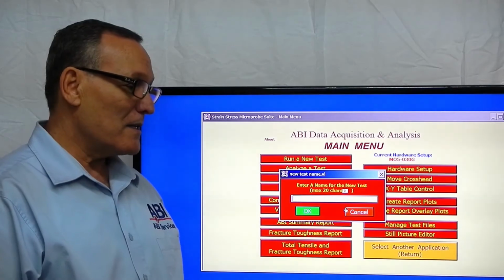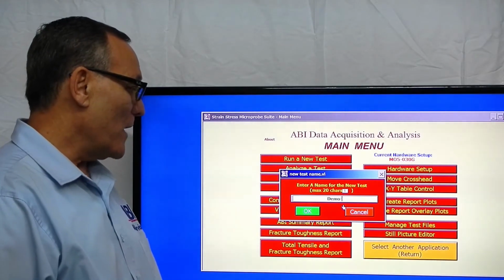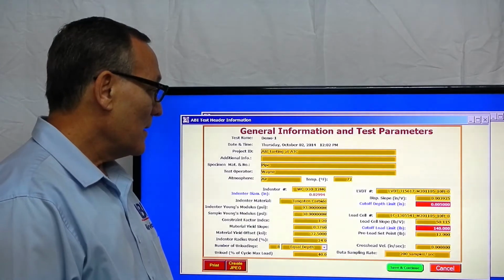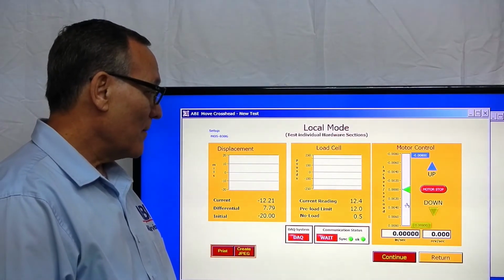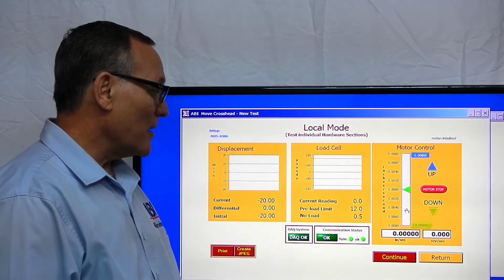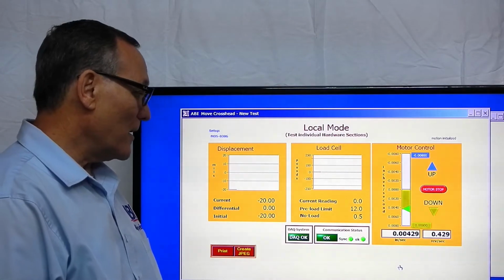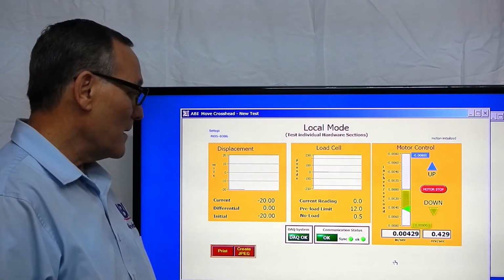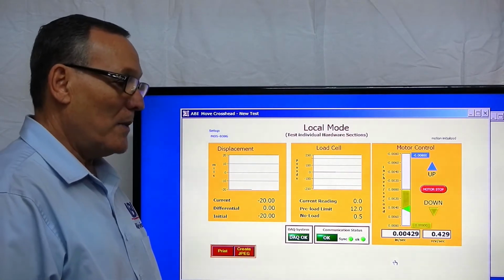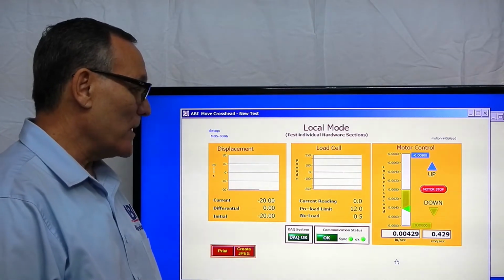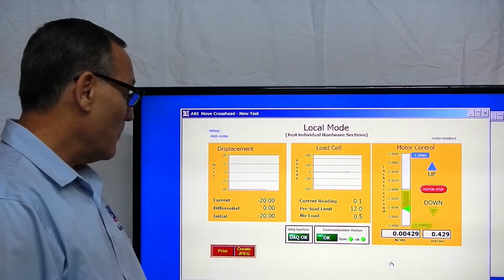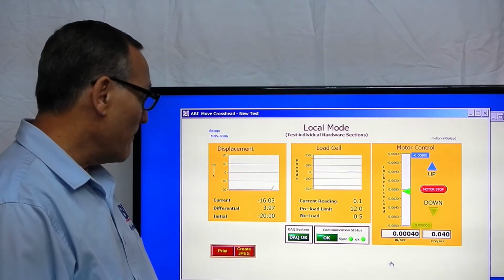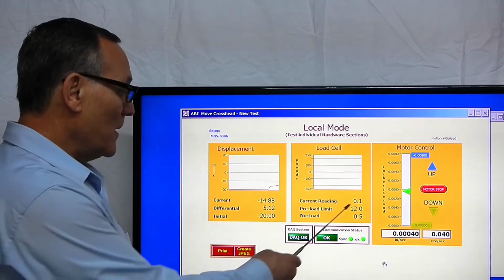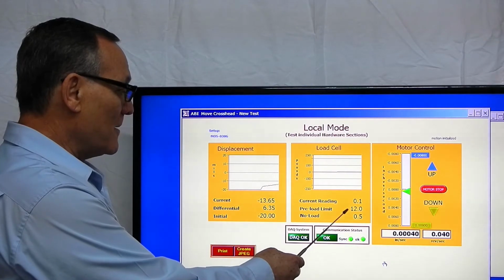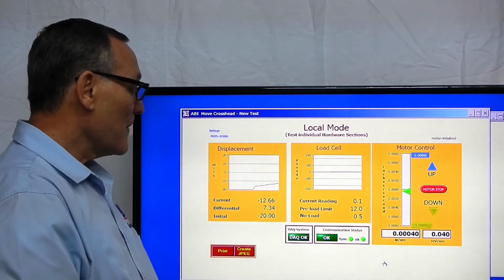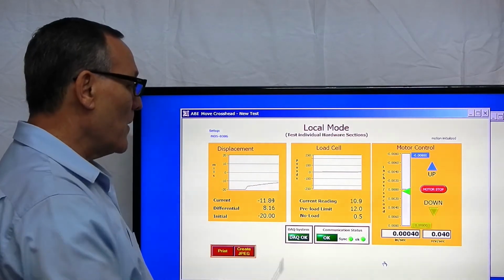This is a demo of an ABI test on a pipeline section. So we start the test by typing the test name. Now we are bringing the indenter to contact the test surface to apply the multi-cycle indentation with intermediate partial unloadings. Once the indenter applies the preload, the test is going to temporarily stop so we can go to the next phase of the test, the cyclic loading with intermediate partial unloading. So now it's applying the preload, and you're going to see this number increase until it reaches the 12-pound preload and will stop. Now it is applying the preload, automatically stopped.